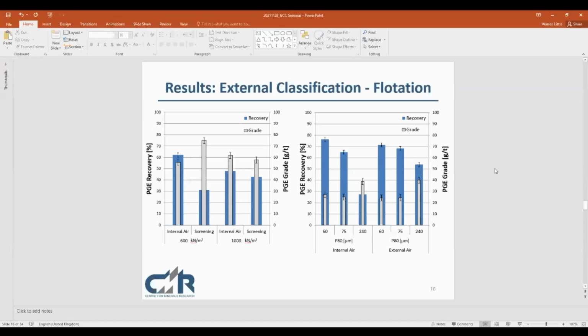For the air classifiers, looking at the finest grind, the P80 of 60 microns, we see the internal air classifier recovery higher than the recovery for external air classifiers. This again is linked to a particle size distribution change. The external air classification product has a significantly large coarse component, which likely would have had less liberation than the internal air classification product. If we look at the center figures, the 75 micron P80s, this is where we had almost identical particle size distributions, and we're seeing an improved recovery for the external air classifier product.